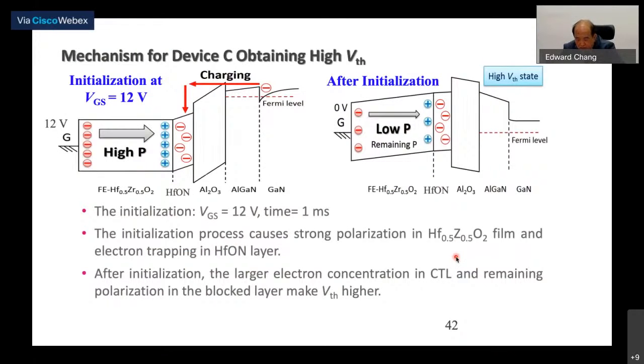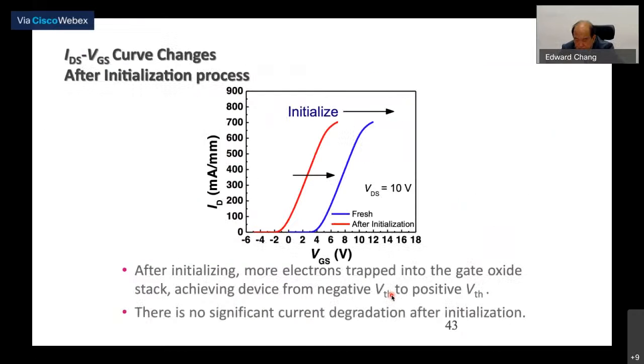And this is how it turns on. You can initiate with 12 volt for 1 millisecond and you get polarization. You can charge the HfON layer and put in a polarization. After initiation, the larger concentration in the charge storage layer remains there, and the polarization for the ferroelectric remains there, and the blocking layer will keep the charge in the charge storage layers. This shows you the IV curve of this device after initiation. You can see that after initiation, more electrons are trapped in the gate oxide.